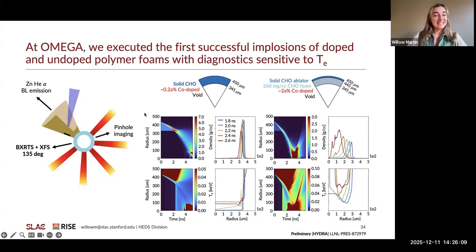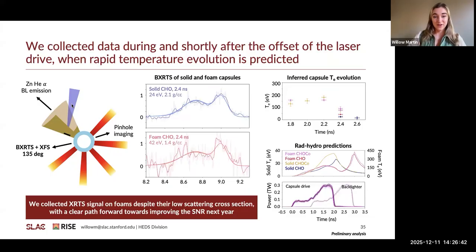Here, the target is heated not via direct laser heating, but by compression using long pulse lasers, and is probed by hard X-rays generated by a zinc helium alpha source, a zinc backlighter foil. After collimating these X-rays through a slit, which sat in our half cone configuration, X-rays propagated through our converging solid and foam targets to characterize the plasma conditions using a combination of fluorescence spectroscopy and X-ray Thomson scattering.